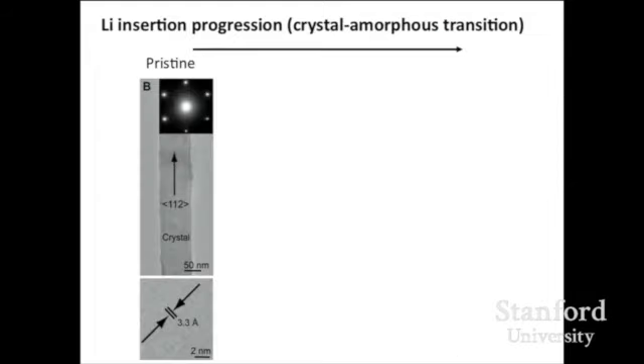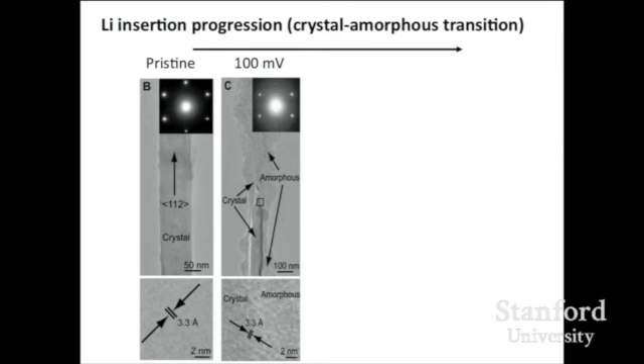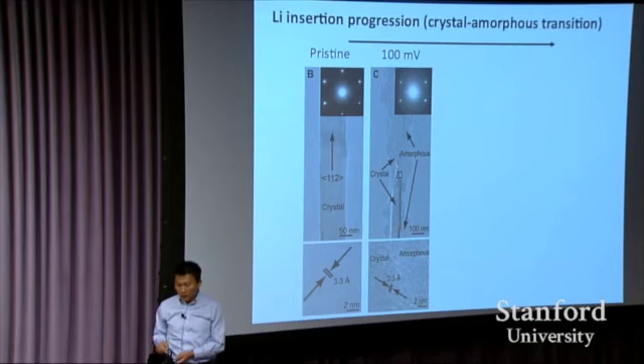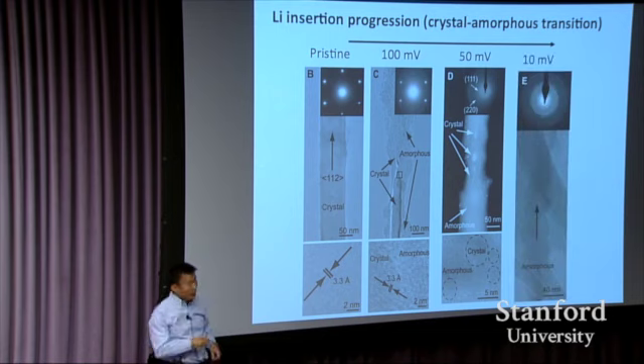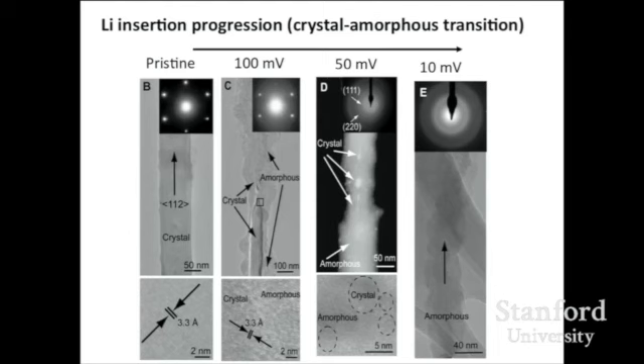And then we started to find out that this change is really dramatic. This is a single crystal silicon nanowire to start with. You put lithium in, and you see this become amorphous. This remains partially crystalline. Eventually, the whole thing becomes amorphous. This big volume expansion is happening. What this really confirms is that crystalline silicon becomes amorphous. Lithium comes in, breaks all the silicon-silicon bonding, and reforms lithium-silicon bonding. At room temperature, silicon and lithium's mobility is limited. Silicon and silicon cannot reform and come back to the crystalline phase, so they stay as an amorphous phase.